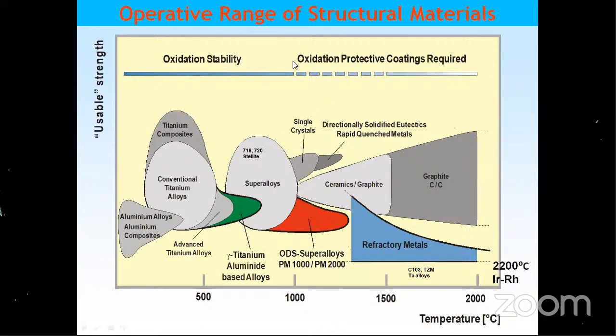From here, whatever we have, refractory metals, ceramics, graphite, all of this needs a lot of protection coating from oxidation. For graphite we give a silicon carbide coating, and refractory metals are given special coatings which prevent the material from oxidation. We use a lot of refractory materials like columbium, molybdenum, etc. Tantalum we also use, but columbium is lighter, so it is more preferred and is easy to deform. So they are the most preferred refractory alloys.